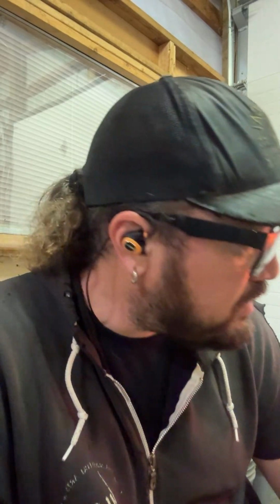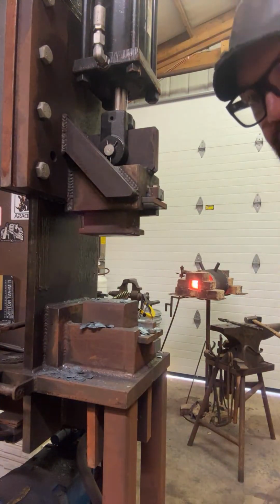Yeah, and my forging dies are 4 inches wide, so I've got to do it at that 4-inch height. So I have to at least reduce this billet from 6 inches to 4 inches. So that's a 33% reduction right there. That feels like a pretty good reduction. By the time this billet's done though, we're going to get through probably at least a 50% reduction in height. All right, let's get this billet out here. Let's do some forging.